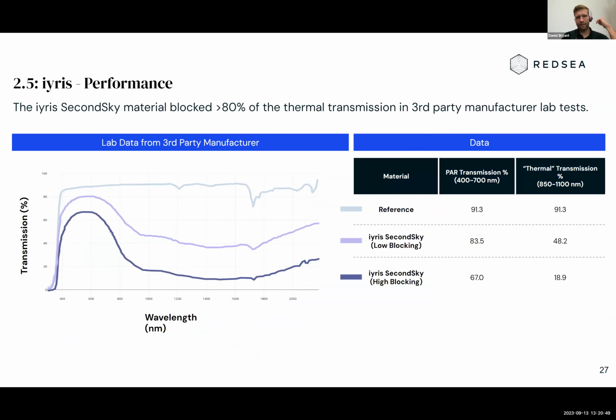And what does it look like as a finished product? This is a UV-vis transmission graph, going from 0 as opaque up to 100% as transparent as air. A normal polyethylene film is the lightish one at the top, which is our reference. You can see that by adding different concentrations, so adding more into the film, we're getting a higher NIR blocking. And we can vary this around.